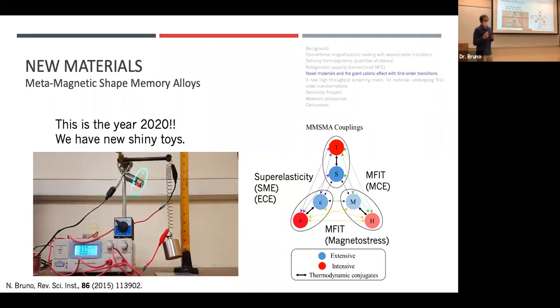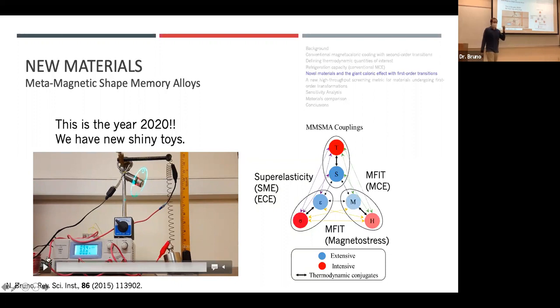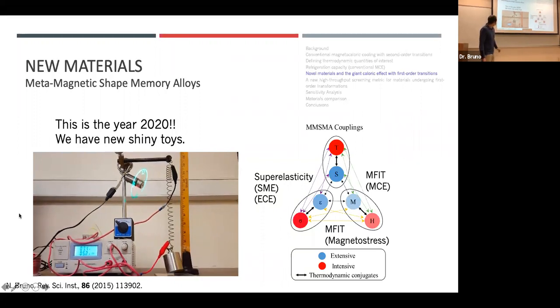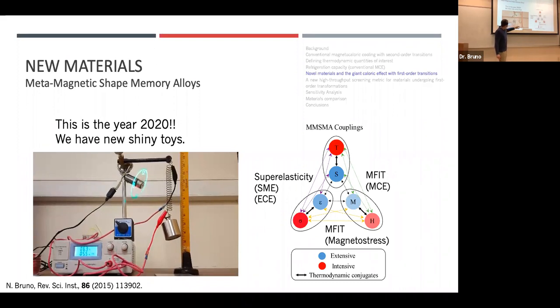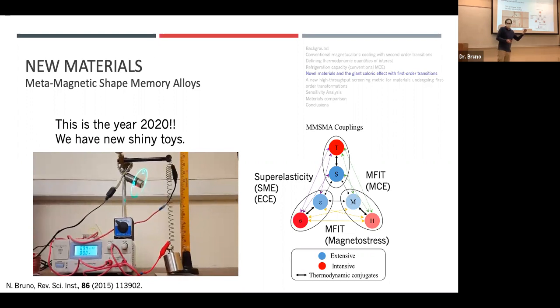In the video you see repeating here is a nickel titanium shape memory alloy that's in my lab. It's not magnetic, but it's a demonstration of thermomechanical actuation, nickel titanium. We're actually performing mechanical work by heating this spring up. So if we could play that again. So I have a weight dangling on this nickel titanium spring. I'm sending current through it, about 5.5 amps, which is causing joule heating. I'm raising it above some critical transformation temperature, which is transforming the microstructure from a low temperature martensite to a high temperature austenite. And I can do this again and again. It's not going to fatigue the material. There's been some studies on this, but it's not the point of the talk. But it's cool to watch.